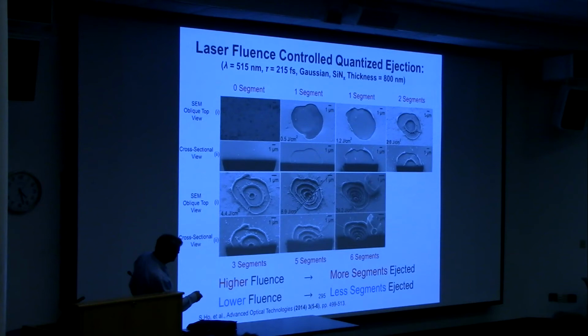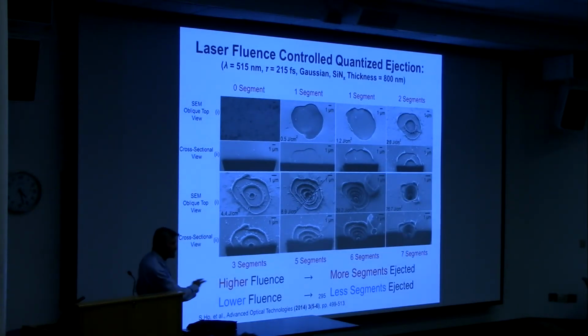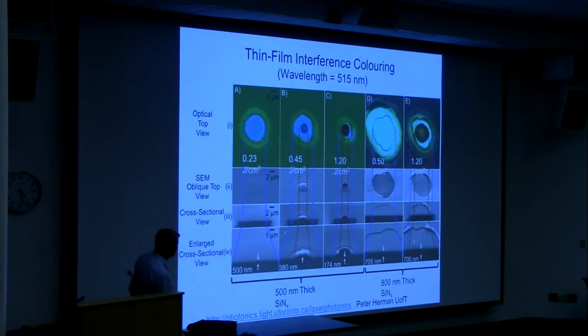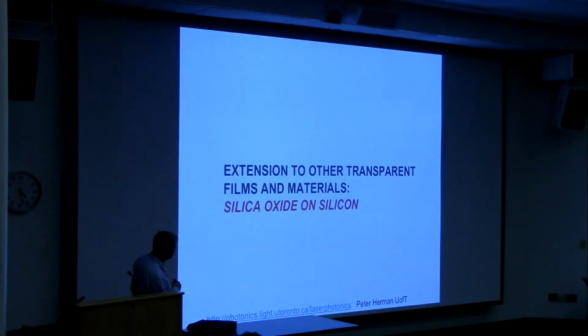And you can see that the material survives. There are parts of those half wavelength thick zones still stuck on. So this is a really new kind of horizontal cleaving method in thin films. When you remove fractional layers, you can do coloring. Each of these spots was made with a single laser pulse, so you could do 1 million per second with today's technology. So you could think of new ways of patterning and marking, which is really important for identifying different manufacturing processes.